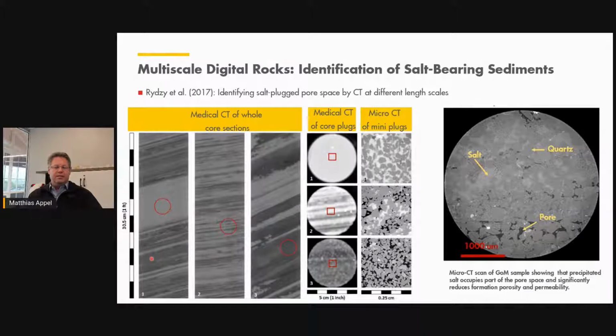So you see highly bedded, thinly bedded formations, but strong differences in the CT appearances. Taking plugs at the indicated locations here of the core shows you already on the medical CT scanner very different kind of structure information. Laminations, much more of a homogeneous rock, a much tighter rock here. If we then take mini plugs at each of these macro plugs, we see a strongly contrasting behavior from an area where the pore space is completely saturated with salt to an area where the pore space is almost free